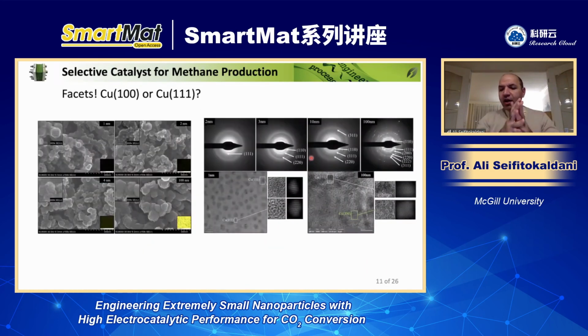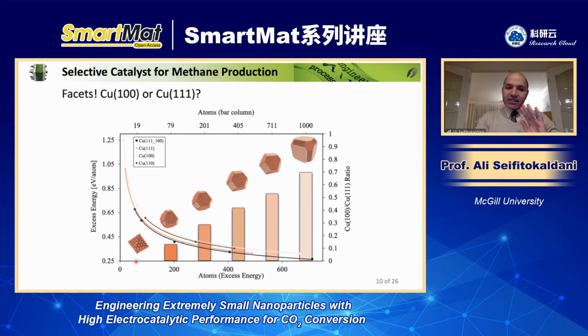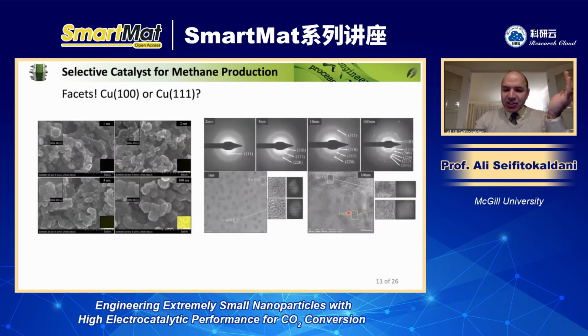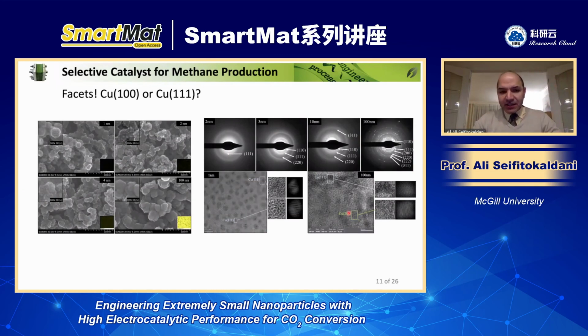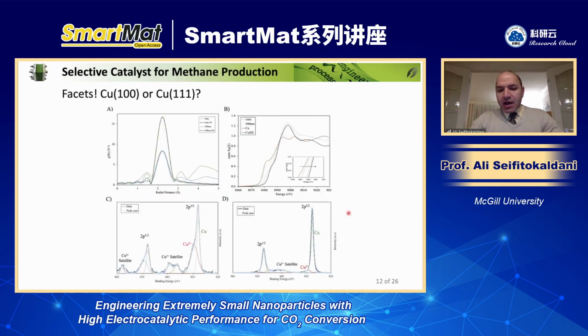So with this knowledge now, we know when you have an extremely small particle, you most likely have a 111 facet. But when you have a larger particle, such as 100 nanometer size, then you have more 100. Then what happens to the reaction mechanism? People investigated this a lot in literature, including myself. We have so many papers where we always use the slab model to do the DFT computation, but not really working on those small particles.